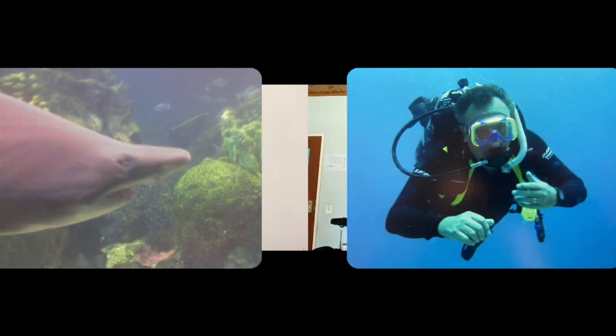So they steered the turtle away whilst I was in the tank, and the shark just swam around near the surface, and I was down near the bottom. And I've got a lovely picture that somebody snapped of me through the plexiglass. So the first dive was to check the condition of the steel, and where the coating of the steel frame had failed, there was a gray corrosion product, which was rather unusual because corrosion products should be brown or rusty. And so we dug away this corrosion product, exposed the clean steel underneath, and there was quite significant corrosion. It was a couple of millimeters.